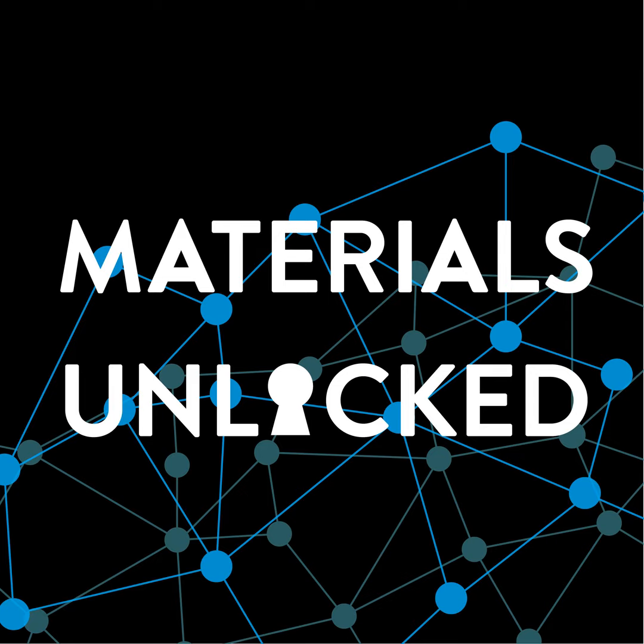But whether you can infinitely recycle steel or not is debatable, because the more you recycle steel, the more you build up concentration of elements like copper and nickel that you can't easily remove, and they start to affect negatively the properties of your steel. So there is that problem with constant recycling. You start to build up these what we call residual elements, and they tend to be harmful to the properties of steel. So that's the first challenge. It's one of the first challenges.